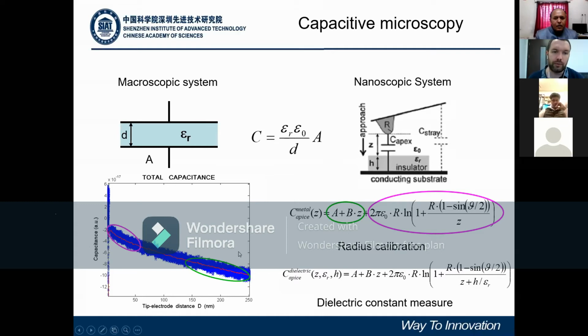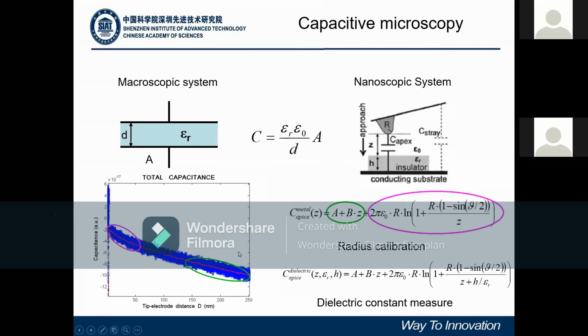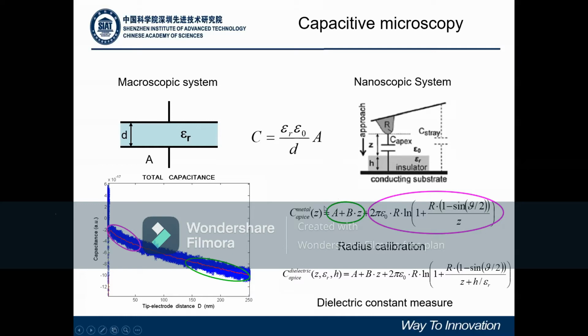While the probe is approaching the surface, it's possible to visualize the linear contribution coming from the cantilever, which is large. And then the last part near the electrode, at nanometer distance, where the capacitance has a behavior more than linear, plus a logarithmic part. This part has a nanometric resolution, and from it a calibration of the probe radius for the electrical contact can be done.